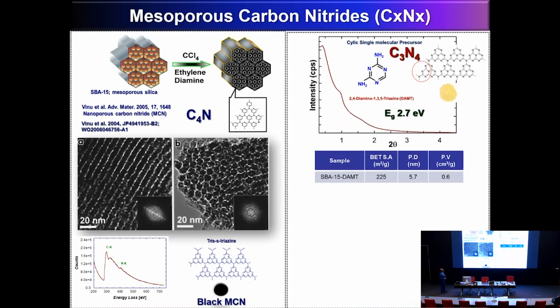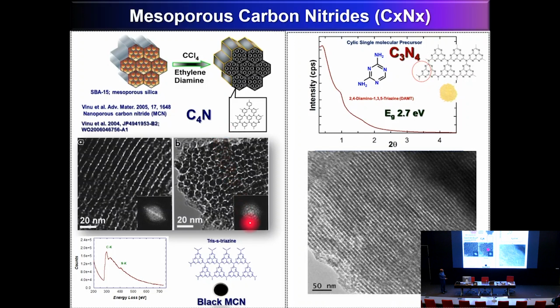To have a carbon nitride with the C₃N₄ stoichiometry with well-ordered porous structures, what we have done is integrate the templating strategy with the diaminotriazine molecule. This undergoes polymerization inside the nanochannels at high temperature, and after removing the silica template by sodium hydroxide, you will get a highly ordered carbon nitride. This is a low angle X-ray diffraction pattern. You can see there's a sharp peak, and that indicates that it has ordered porous structures, and the surface area of the material is 225 meters squared per gram. You see, the high surface area is coming from the well-ordered porous structures.